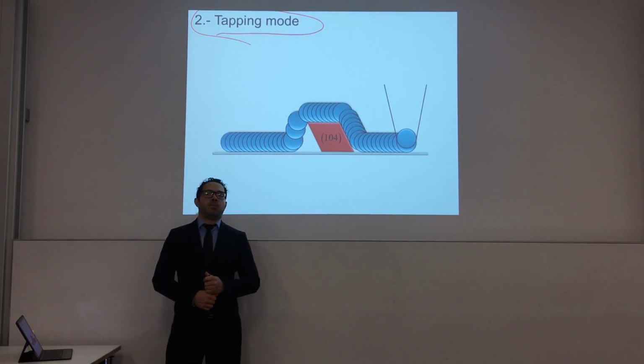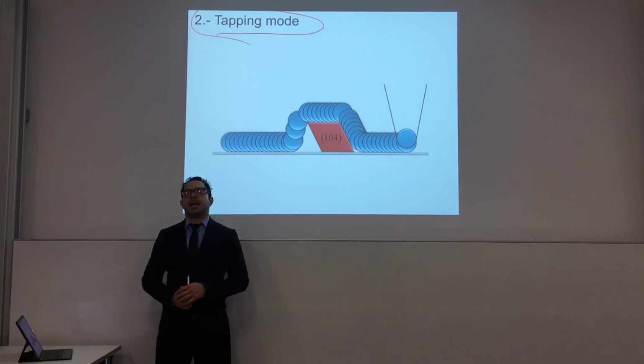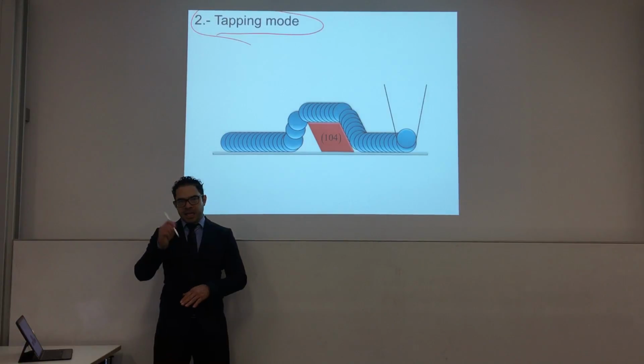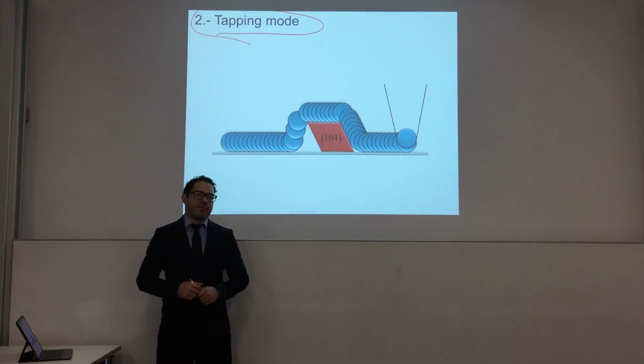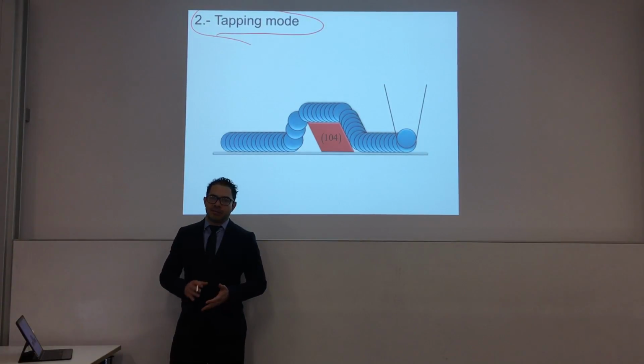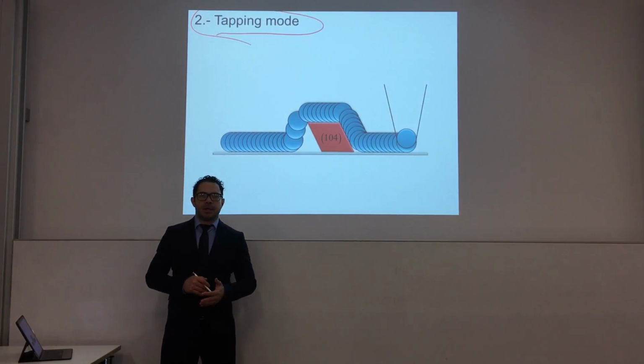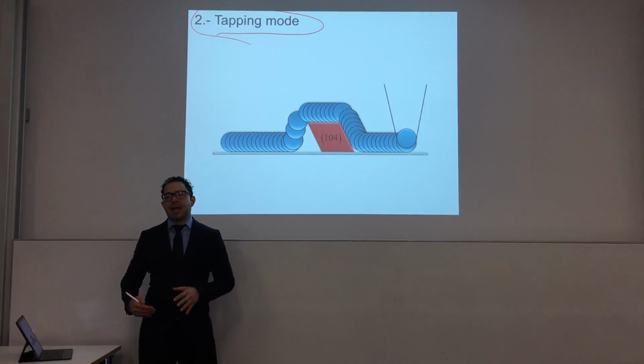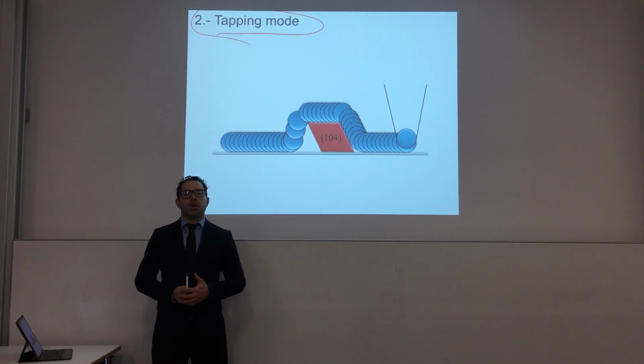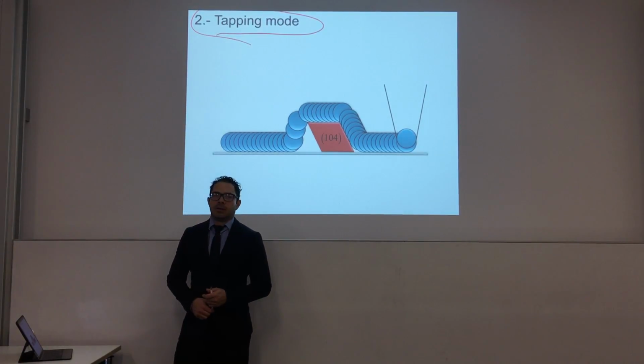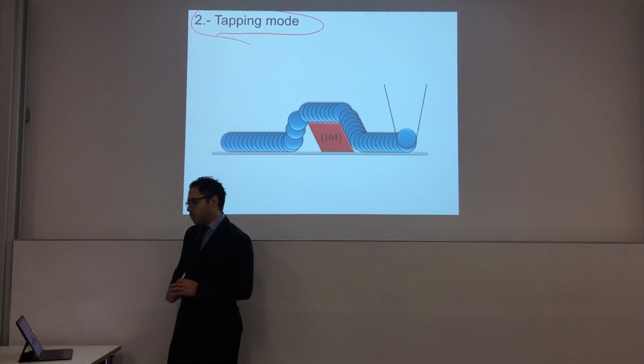The advantage of tapping mode with respect to contact mode is that since there is only intermittent contact with the sample at each oscillation cycle of the motion, the shear forces will be highly minimized. This is a very important point because now you will be able to visualize or to analyze samples that are very soft, even liquids you can analyze using atomic force microscopy in the tapping mode.